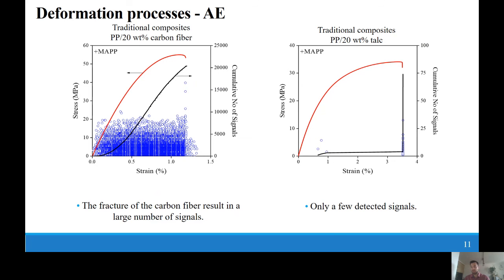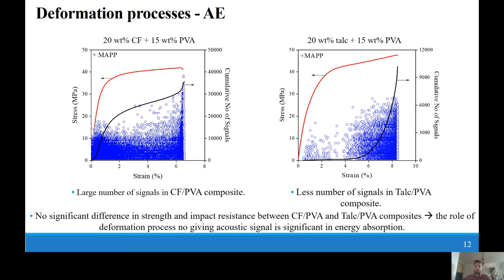Negligible amount of signal is detected in the talc reinforced composites due to the fact that the small particles don't give a signal which can be detected by the acoustic emission method during the debonding. On the next slide, I will present the acoustic results of the hybrid composite of the composition shown here. For hybrid composites, a much larger number of signals was detected because of the PVA fibers.